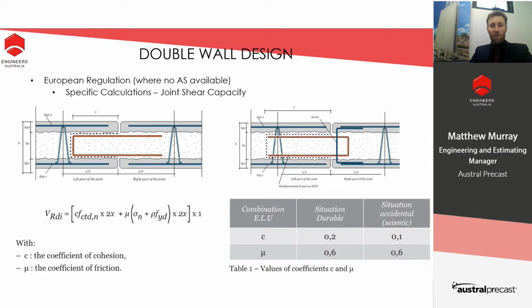The difference with this is that we can get the full tension lap and have the connection with the U-bar to actually increase the capacity of the joint, because there is a contribution at the joint level from the U-bar crossing the interface from the precast to the core concrete, as well as the fact that we are having essentially a cogged lapping at that connection. When it comes to the coefficient of friction and cohesion to use, there are 2 numbers which are the same as what we would use under AS 3600. Typically a c of 0.2 and mu of 0.6 for most cases, and under seismic conditions, the coefficient of cohesion c should be reduced to 0.1.